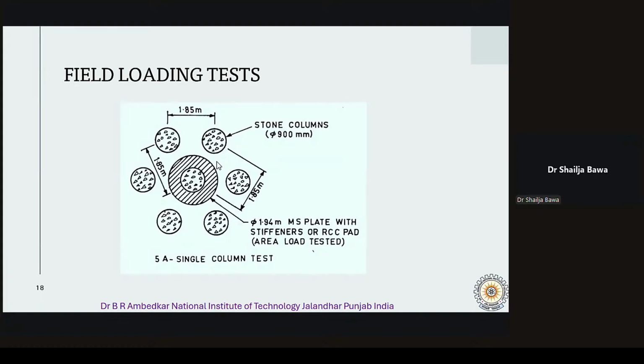Field loading tests. Now, as I told earlier, irrespective of the method used to construct the stone columns, the initial load test should be performed at a trial test site to evaluate the load settlement behavior of the soil stone column system. So for the initial load test, in order to simulate the field conditions of the compaction of the soil, minimum 7 columns for a single column test and 12 columns for a 3 column group test may be constructed in a triangular pattern. So here you can see for the single column test, we place these columns in this arrangement. Okay, so the spacing you can see as per the code, and what is the diameter of the stone columns as per the code for field loading test.